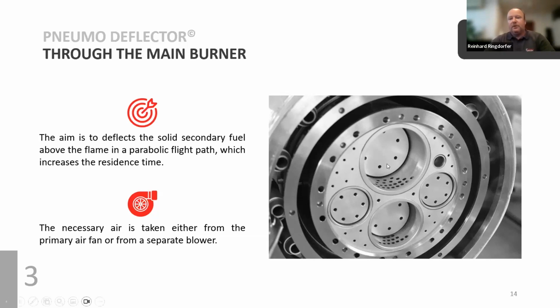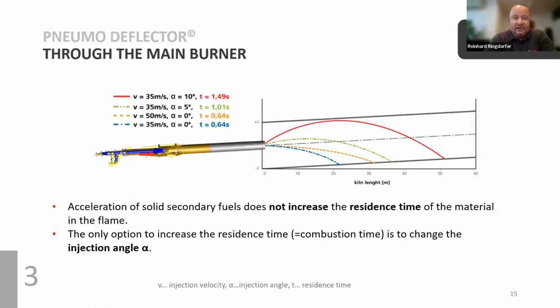Here in the picture, you can see a burner with two of these secondary fuel pipes, and you can see the openings here with different angles. Usually this is supplied by the primary air fan, can also be supplied with a separate blower, and can be adjusted from the cold side of the kiln. Here you can see the theory behind this. We have tried different approaches, increasing the injection speed, using swirl and so on, but ultimately only the deflection of the particle above the kiln axis will give you an increase in residence time and therefore more time for combustion of the particles.